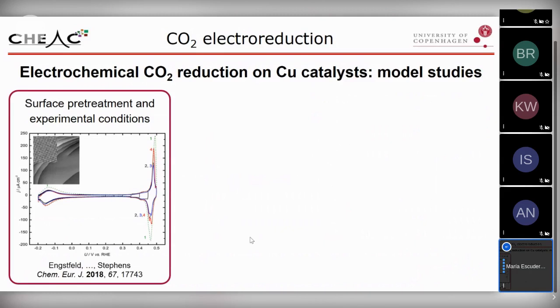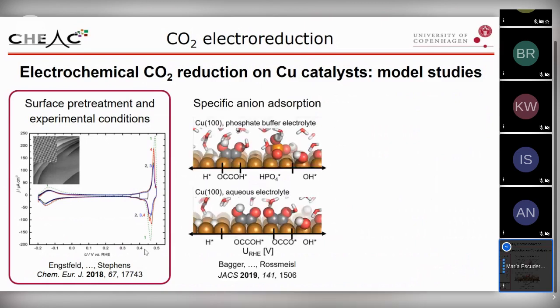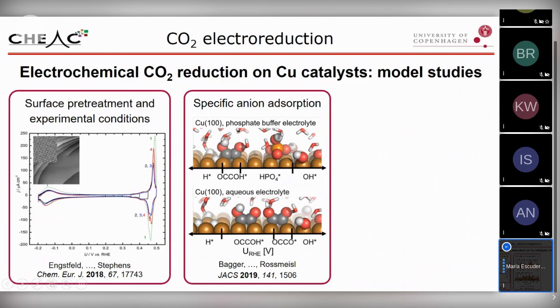From the literature, and this is particularly from Ivan's work, we know that both the surface pre-treatment and the experimental conditions are very important and will affect the structure of our electrode. So the preparation of our catalysts, in the case of model studies using, for instance, single crystals, is crucial. We also know that the adsorption of electrolyte species and anion species will influence the structure and the CO and CO2 reduction.